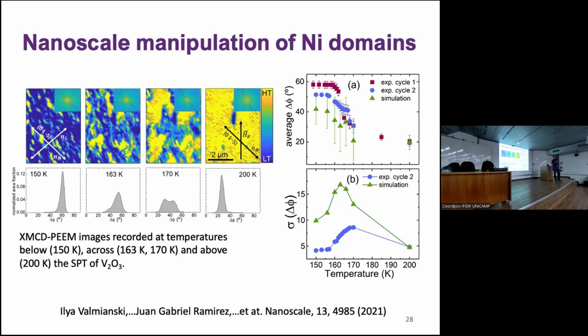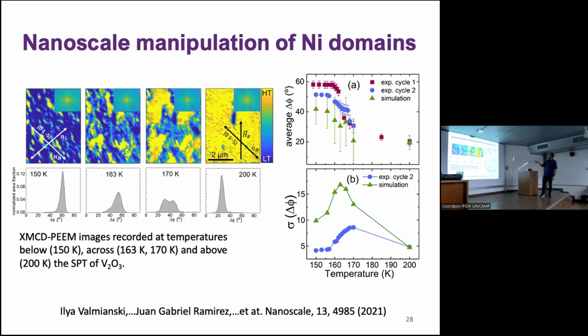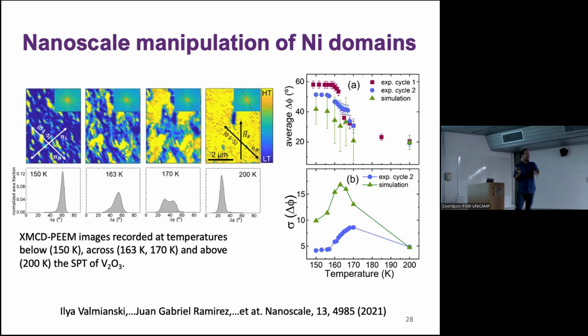And those domains, if you calculate what is the average angle of the domains, you will see that they rotate, as you can see here, more or less 45 degrees. Okay, so the average rotation of the domains. And that actually matches perfectly the FMR result. And then we were very happy because this is what we thought about from the beginning, that the sample breaks into domains.